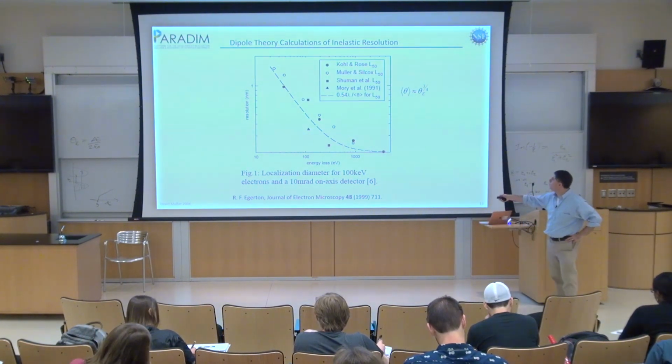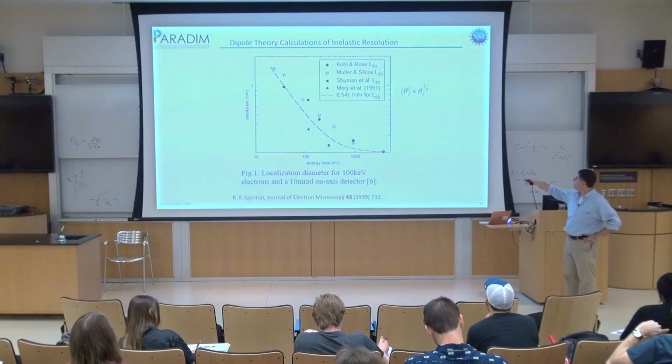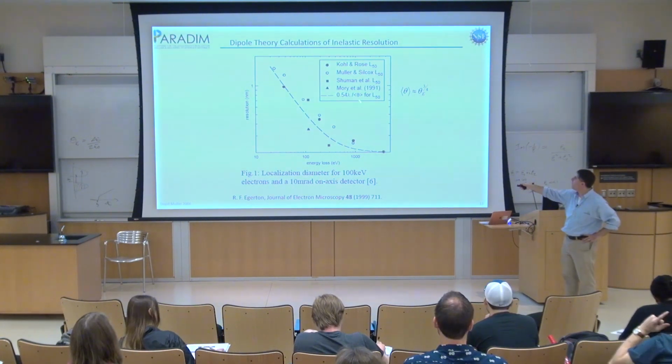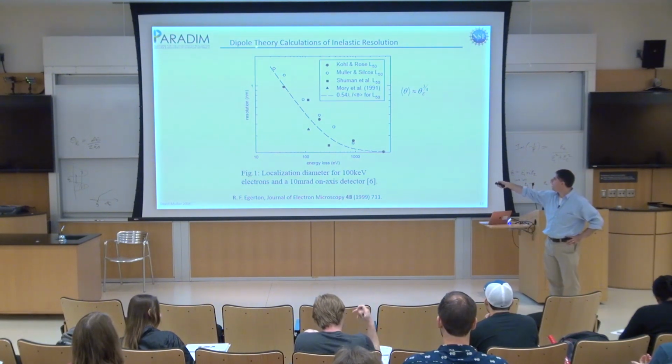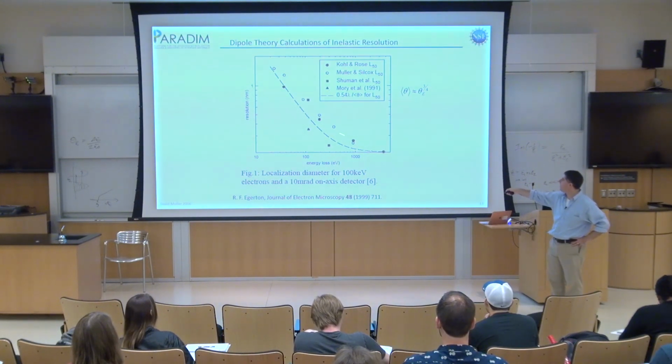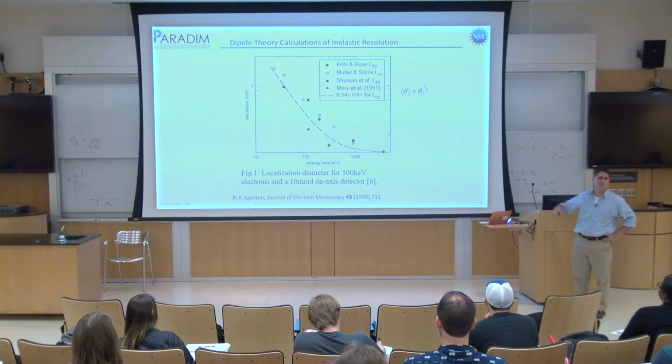The spatial resolution that you would guess, if you're looking at a 50% or an 80% radius, you would take the scattering angle to the 3/4 power, multiply it by the wavelength, and put a fudge factor in the front. That would be an analytic guess, which is being shown over here. And here is a whole bunch of very complicated calculations of the 80% radius, or the 50% radius, I guess.